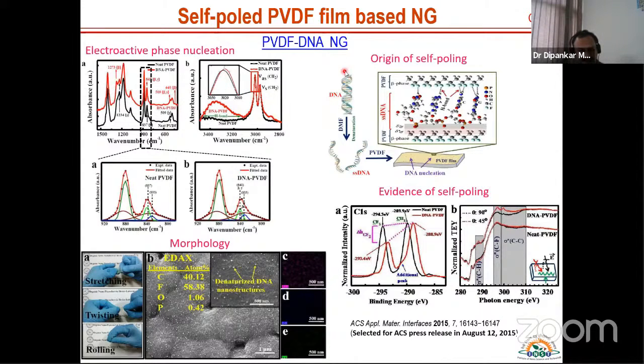What we did, DNA is like this, then we denatured it. That means we cut our DNA, like with scissors. So we have a single strand, and there is a lot of surface charge, and this surface charge interacts with the PVDF chain, and there is an electrostatic interaction that gives rise to this particular beta phase. So we got a very nice beta phase once we put denatured DNA in the PVDF solution and cast it.